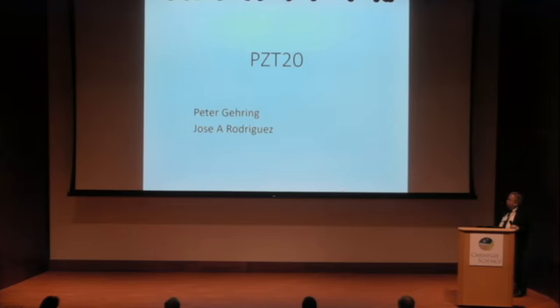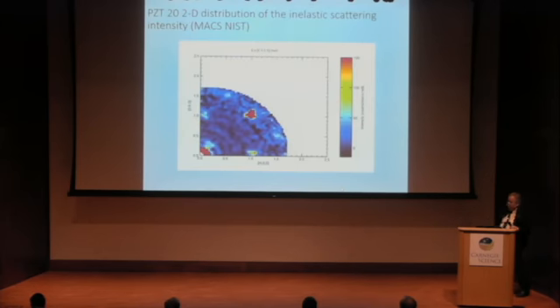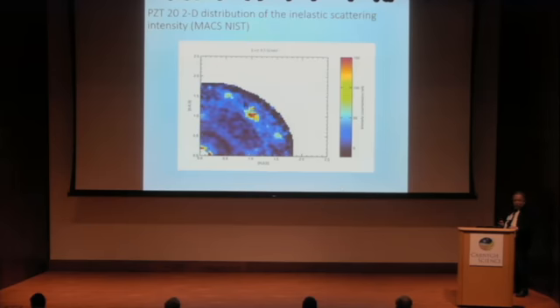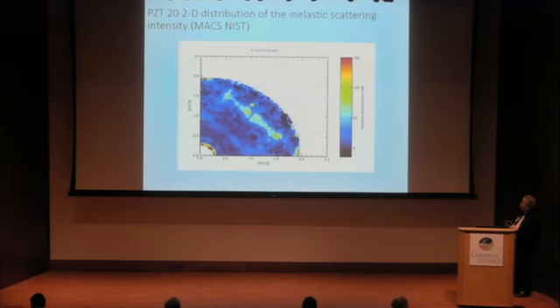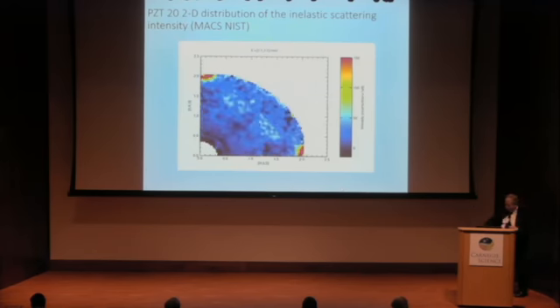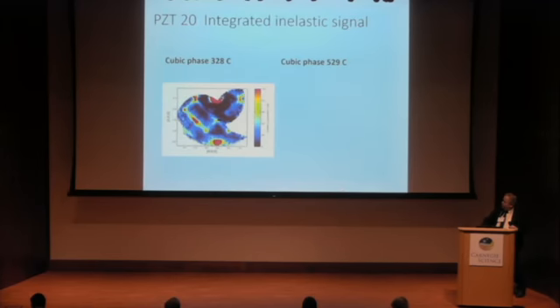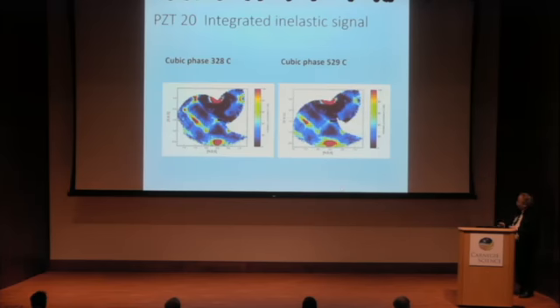And then I just want to show, without any simulation, since we are still working on it, a measurement we did on PZT20 with Peter Gehring. More likely, Peter gave me the possibility to participate in these measurements. So we followed the picture of neutron inelastic scattering in PZT20. If we look at how the intensity map looks in the final integrated signal, you see we do have a peak on one side and next to nothing on the other. We are closer to the phase transition, with a strong peak in the inelastic scattering on one side. Elastic was excluded; it's energy integrated except for plus minus 0.25 milli-electron volt.